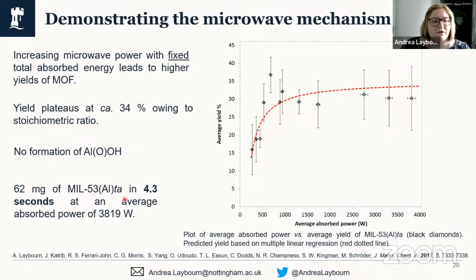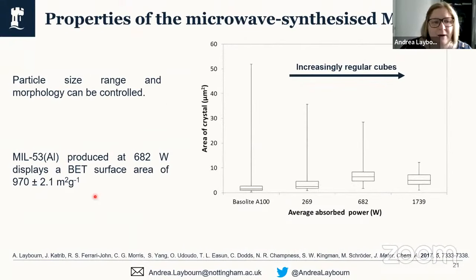And to give you an idea of the timescales and the powers involved in this, we were able to produce roughly around 60 milligrams of the MIL53 with the terephthalic acid incorporated in the pores at roughly around 4.3 seconds at an average absorbed power of roughly around 4 kilowatts. So these are very, very fast reactions. Now, interestingly, we saw that we were able to have control over the properties based on the treatment parameters that we were using for this energy delivery.